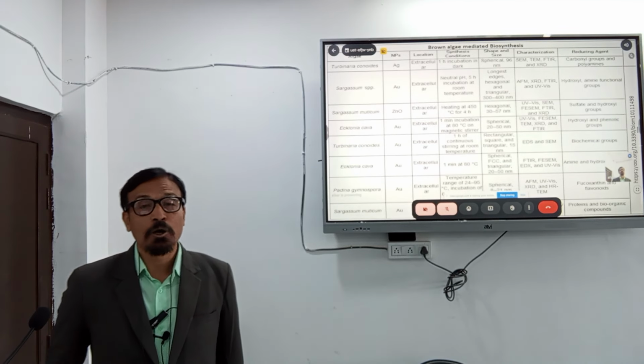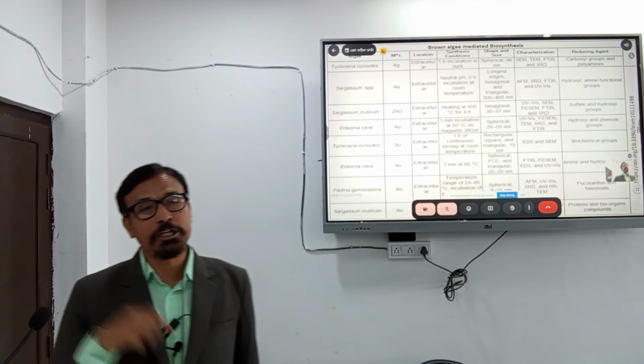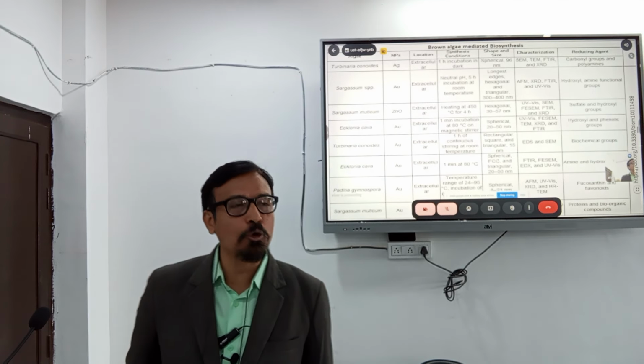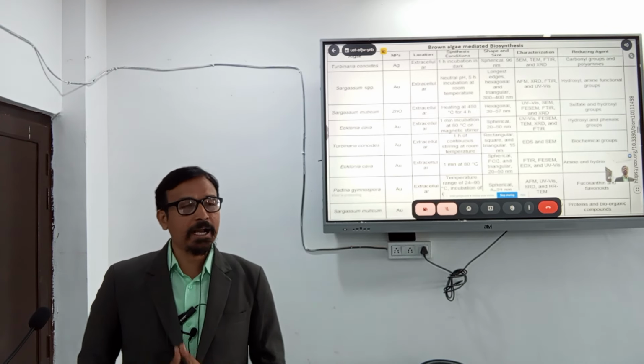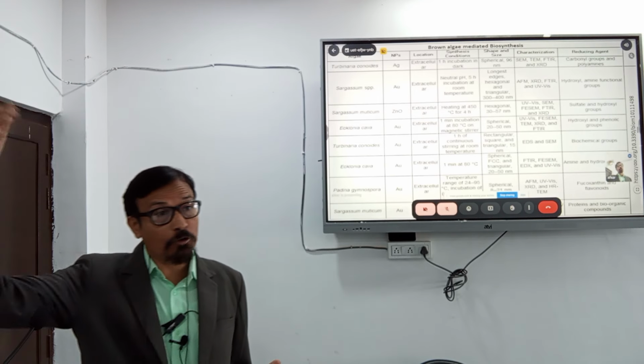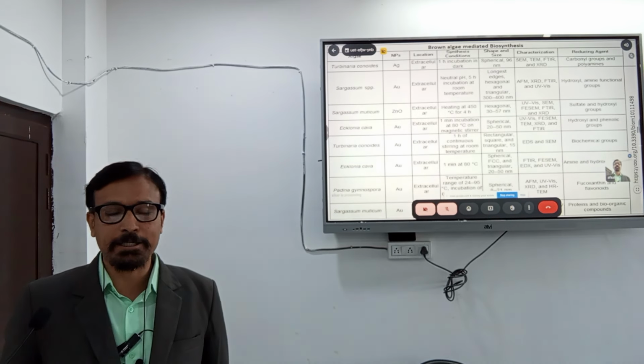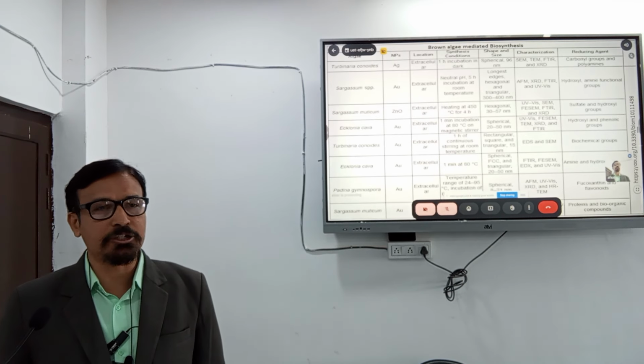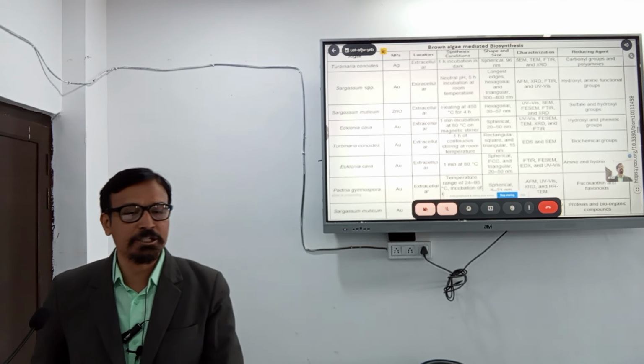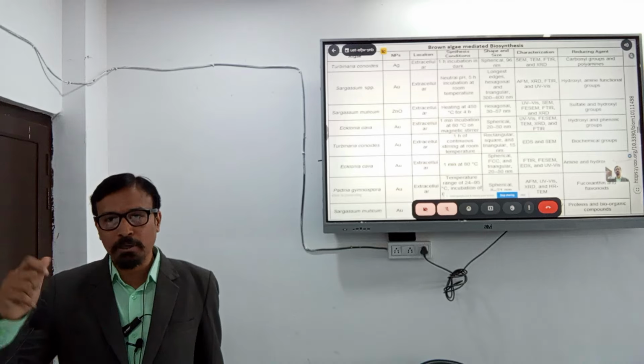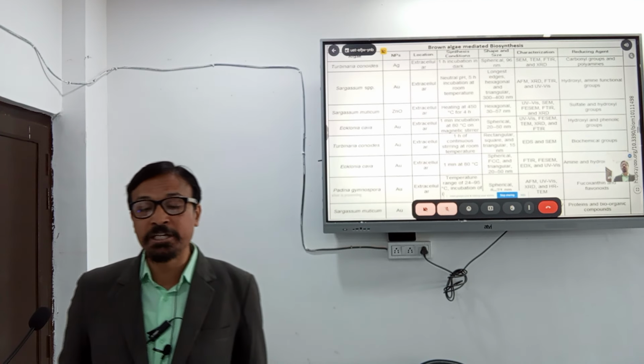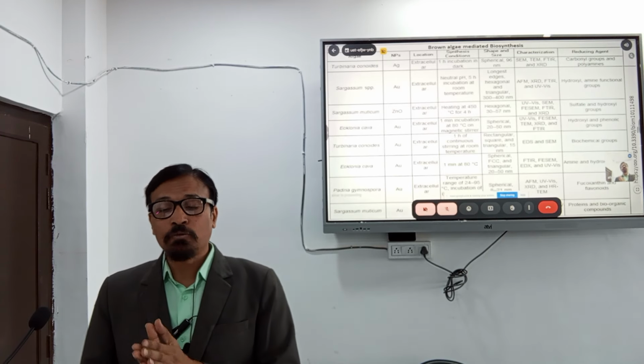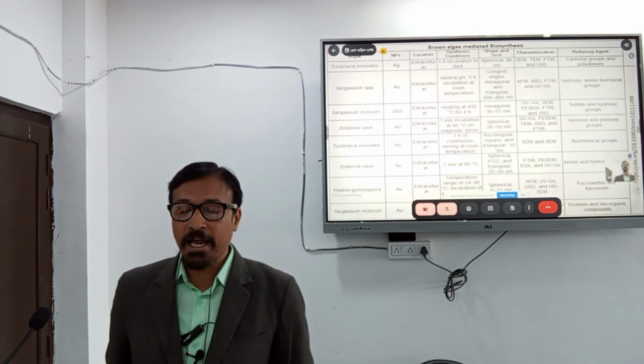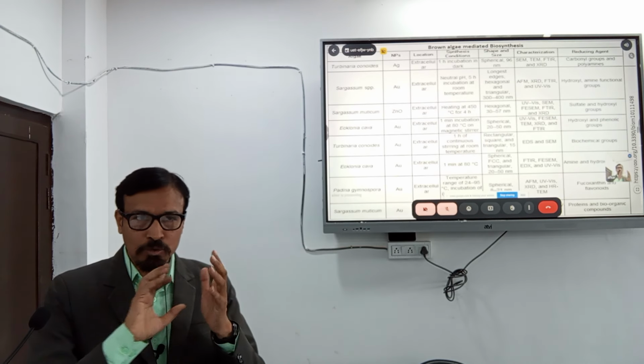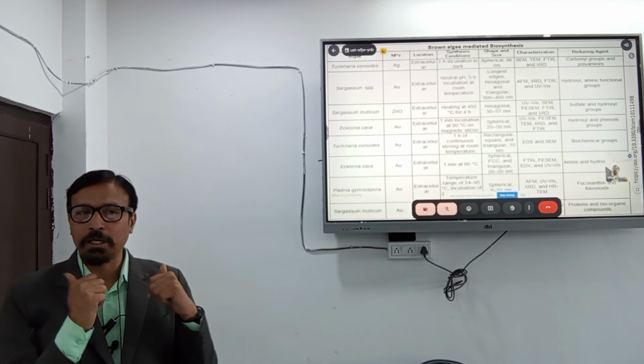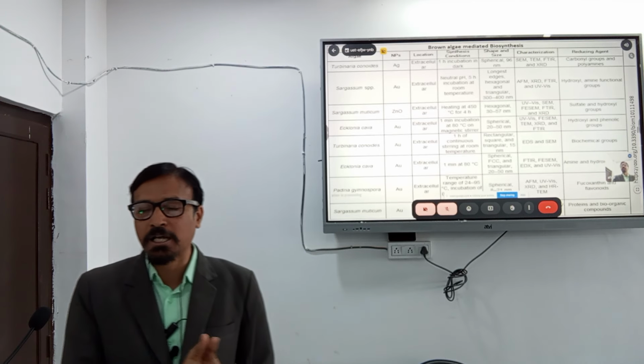Another is Sargassum muticum, with which we can produce zinc oxide nanoparticles, and these are also produced outside of the cell, so the location is extracellular. The synthesis condition is heating at a very high temperature, 450 degrees Celsius. So you can imagine we would die, of course, at that high temperature. At this high temperature, the zinc oxide nanoparticles are produced by Sargassum muticum. Hexagonal shaped nanoparticles will be formed in the size of 30 to 57 nanometers. The characterization can be done with UV-Vis, FESEM, FTIR, and XRD. And the reducing agents present in Sargassum muticum, which reduce the ionic species of the metallic particles, are sulfate and hydroxyl groups.